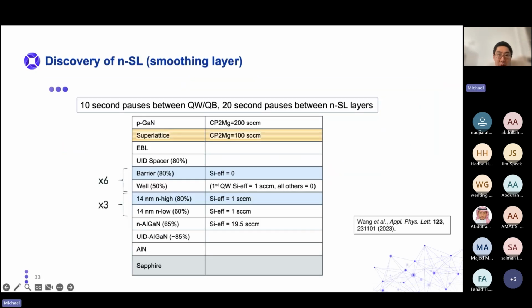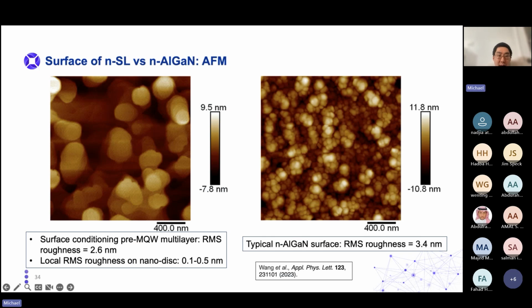And I also just, around this time, discovered this n-type smoothing layer with alternating layers of 14 nanometers of 60% aluminum and 80% aluminum. Three times of this, so 6 total layers, and with growth pauses between these n-type smoothing layers. So these growth pauses basically are when we turn off the metal organic and just let the ammonia keep on flowing. This actually starts etching back the gallium. So at the high temperatures that we're using for the growth, the gallium desorbs from the surface. And what happens is that it conditions the surface.